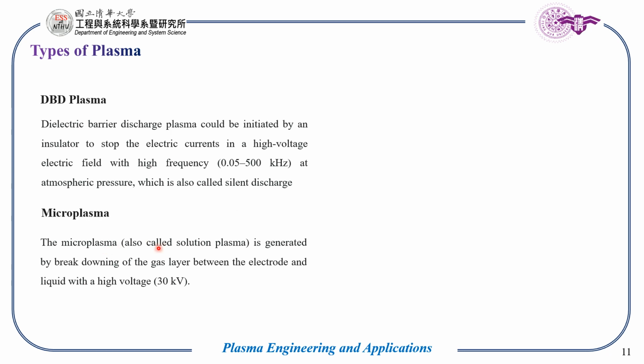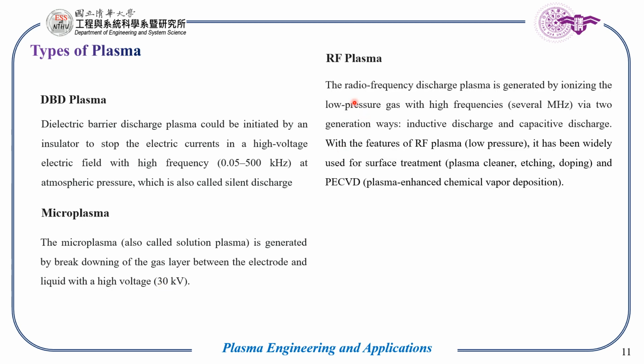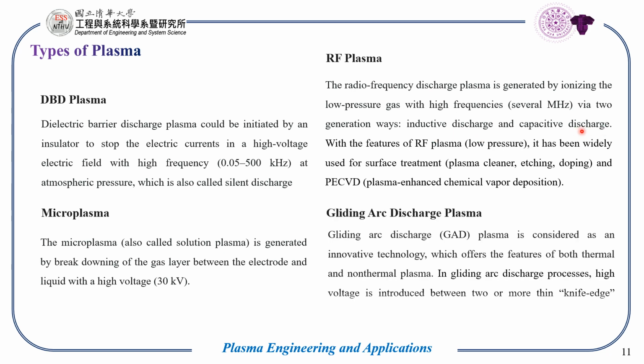Microplasma, also called solution-based plasma, can be generated by breaking down the gas layer between the electrode and the liquid with a high voltage of up to 30 kilovolts. RF plasma, the radio frequency discharge plasma, is generated by ionizing low-pressure gas with high frequencies, and by two generation ways, that is inductive discharge and capacitive discharge.